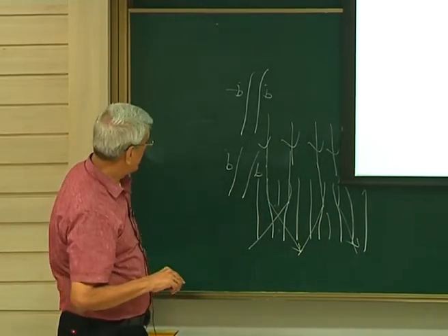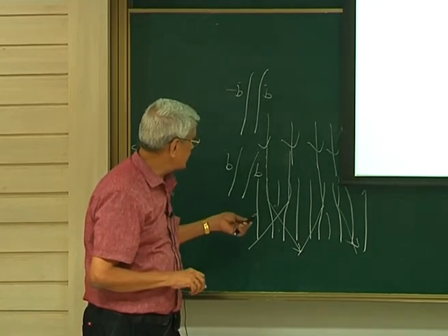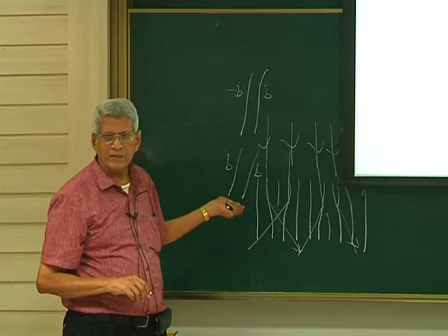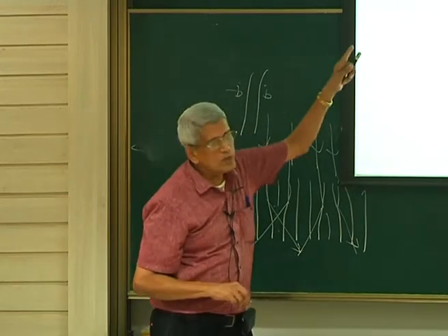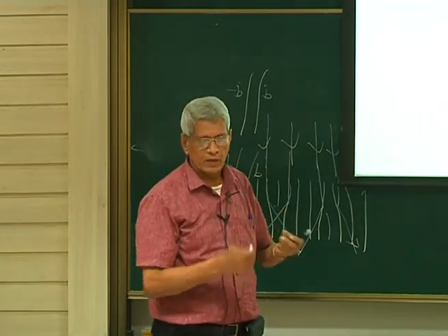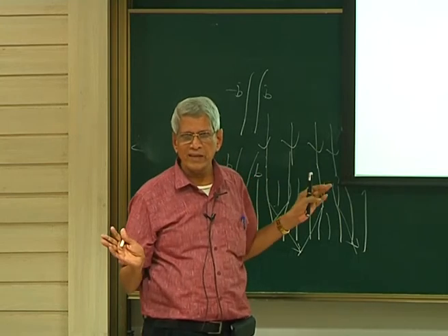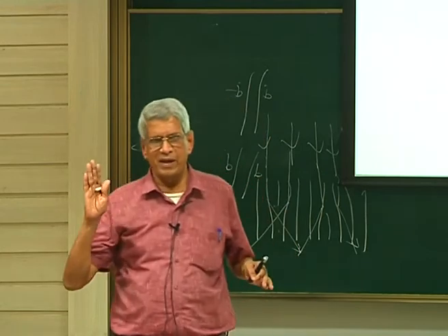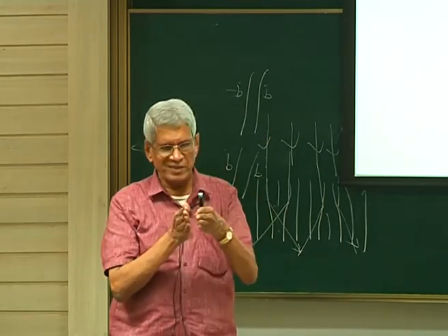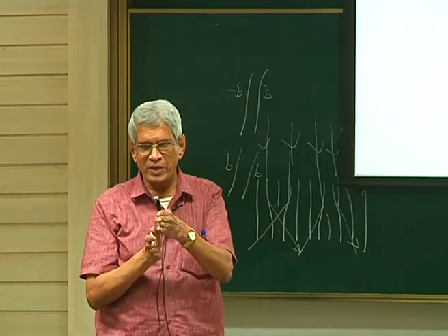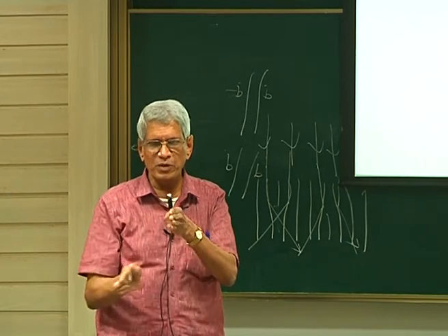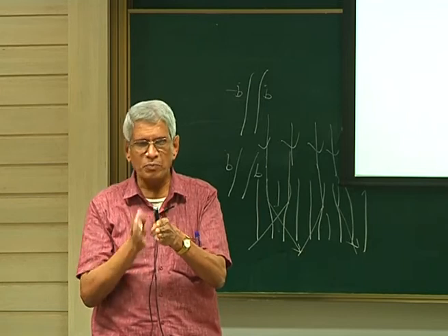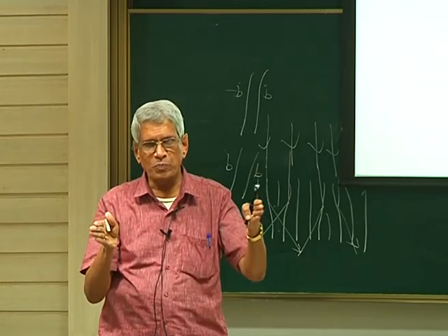The effect of it will be that one is a plus b and another is a minus b. When you see the spacing between the dislocations, as I mentioned earlier, the image we see is essentially not the actual image of the dislocation. On either side of it we see that image. So if it is a plus B, an image comes on this side, and minus B will come on the other side.